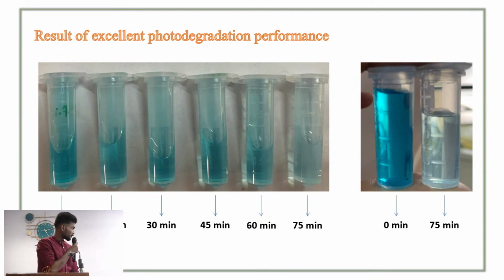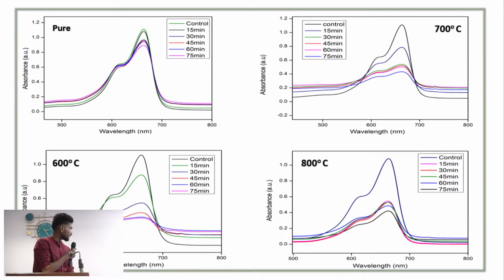These are the results of the photodegradation of three different samples over the time interval of 0 to 75 minutes. I have plotted a graph using Origin, and we can see the pure methylene blue dye solution with no catalyst shows only slight changes. Compared to that, at 600 degrees Celsius, degradation occurs. At 700, there is a larger degradation compared to 600. At 800 degrees Celsius calcination, lanthanum titanate has a drastic degradation compared to 600 and 700 degrees Celsius.